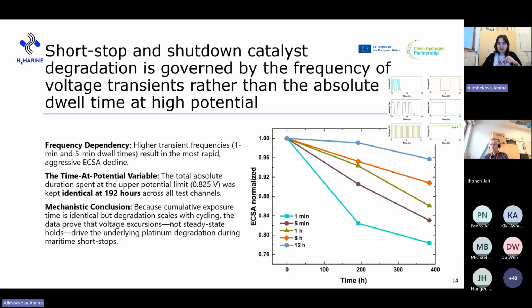As you can see from the curves, the platinum surface area loss is quite sensitive to the frequency of the short stop and shutdown events, where the high frequency short stops at 1 minute and 5 minute hold dwell times showed the largest and most aggressive electrochemical surface area loss.